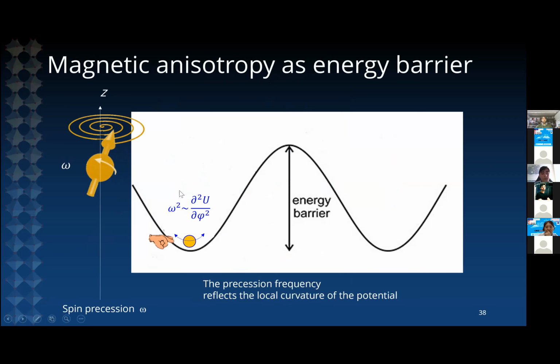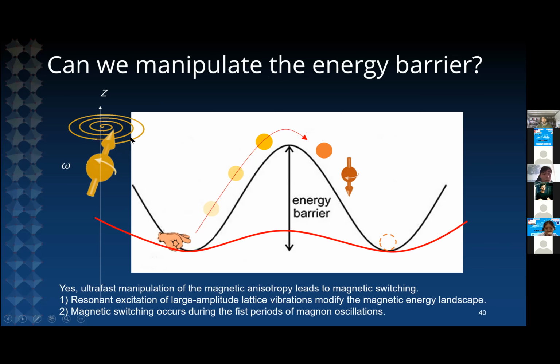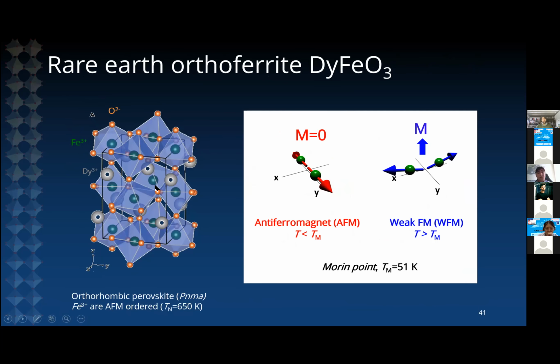So typically, electromagnetic changes in spin orientation are induced by exciting spin precession, and the precession frequency reflects the curvature of the local magnetic landscape. And if this rotation is large enough, you can switch the material from an up state to a down state, for example. And here we investigated whether by manipulating the energy barrier itself through a change in magnetic anisotropy, we could induce transitions between magnetic states. And in our research, we focused on the rare earth orthoferrite dysprosium orthoferrite.